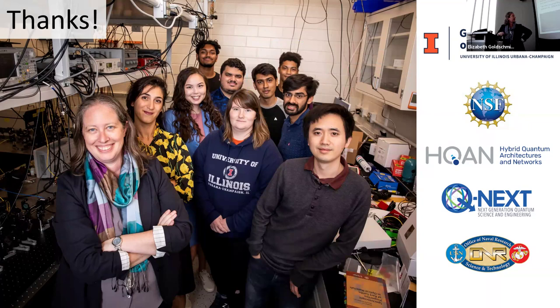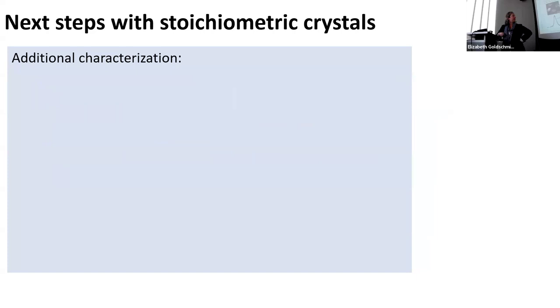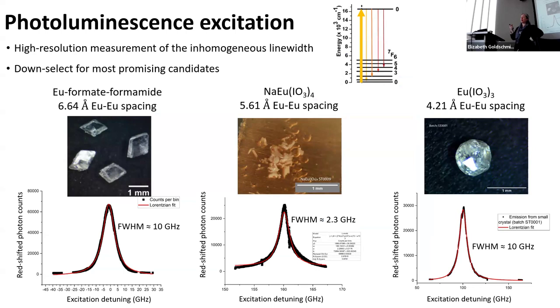Yeah, it's a good question. In choosing, we started off by looking through the literature for papers that have a synthesis method for a europium material where the nearest neighbor europium spacing is at least 5 angstroms, and that we thought we could synthesize. That got us those two metal organic frameworks to start and a couple of other things, including some other oxides that we made, but then we didn't like. So they didn't make it on my slide. That's a relatively short list, though.